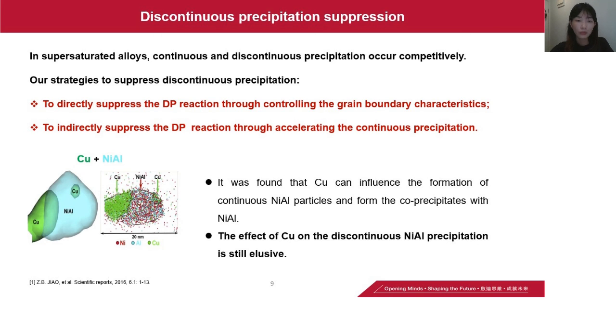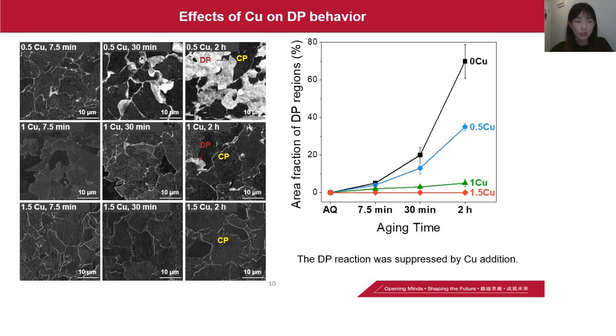In nickel-aluminum steels, it was found that copper can influence the formation of continuous nickel-aluminum particles and form co-precipitates with nickel-aluminum. But the effect of copper on the discontinuous nickel-aluminum precipitation is still elusive. So we add copper in our model steel.